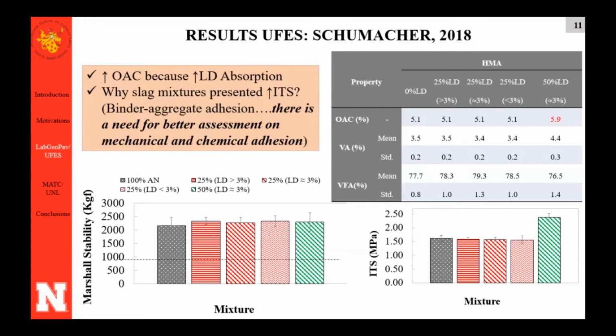This is very good because when you present this to the industry, for HMA plant production, they don't want to increase the binder content. And we can say, well, you can replace 25% and you still don't need to increase the binder content of the mixture. But if you go for a higher amount of replacement, we tried 50%, the binder content increases. And the explanation for us was because slag has a higher absorption. So for higher levels of replacement, you need more binder. But at a certain level, you still can get the same binder content.